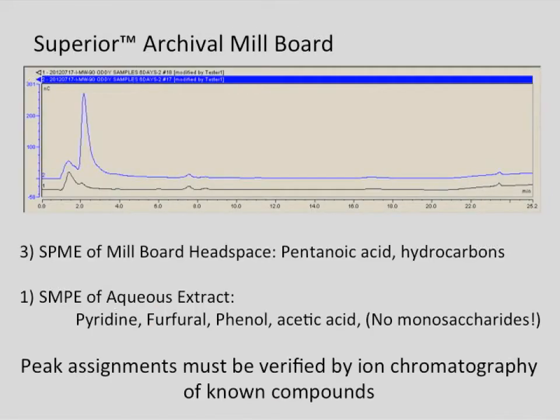For the Superior Archival Mill Board, we did the two tests, and here we did the third one of looking at the headspace and the aqueous extract. For the headspace, where you've got the vial of just the preservation material and you're looking at the off-gassing materials above it, we found a fairly large peak of pentanoic acid and then a lot of long-chain hydrocarbons. Neither of which should show up in our IC, so neither of those are likely this very large peak.